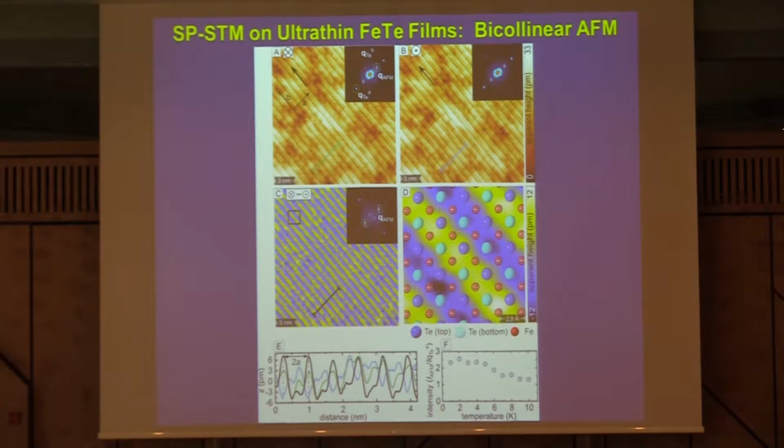So by using a spin-sensitive tip, we see immediately the reduction of symmetry in the pattern we observe. Now we have a row-wise structure here, and immediately we see only the twofold symmetric spots in the Fourier transform. And now we do the same thing as discussed before for the antiferromagnetic monolayer of iron on tungsten 001. We change the magnetization direction of our probe tip, and you see again a phase shift, which becomes clear if we calculate the difference image of these two data sets, and then we basically get a pure spin contrast image here, and you see beautifully this row-wise structure.